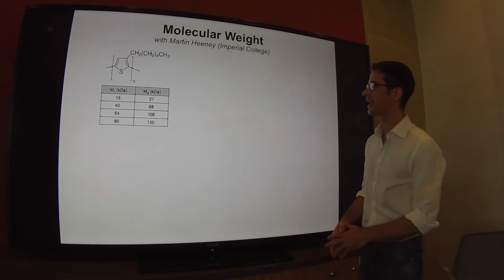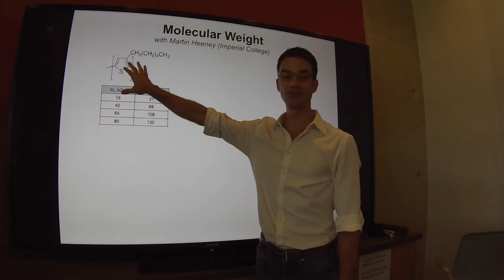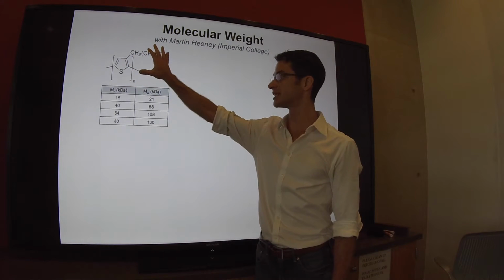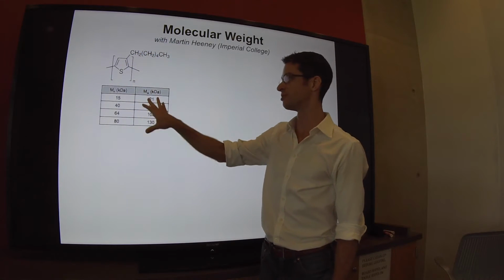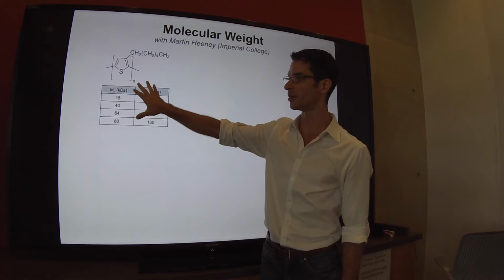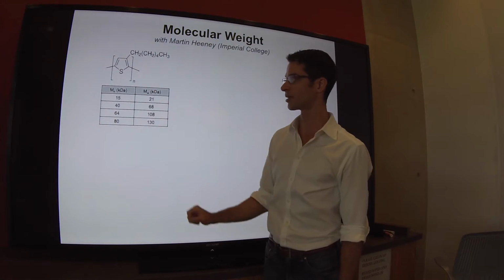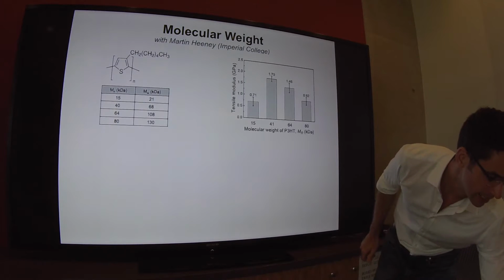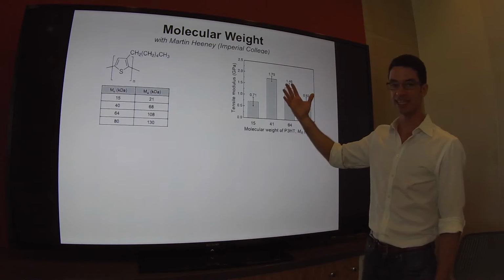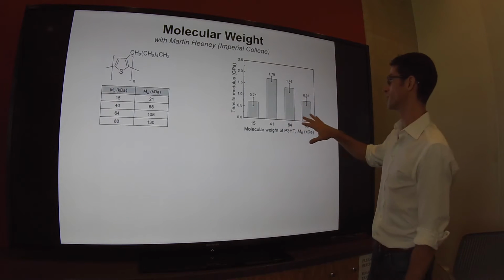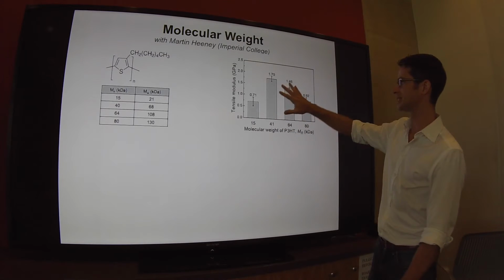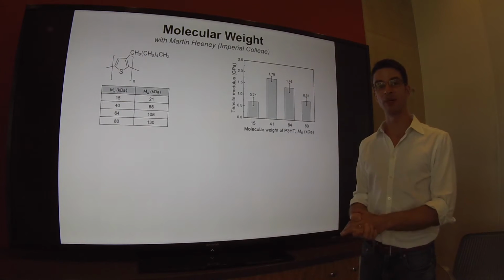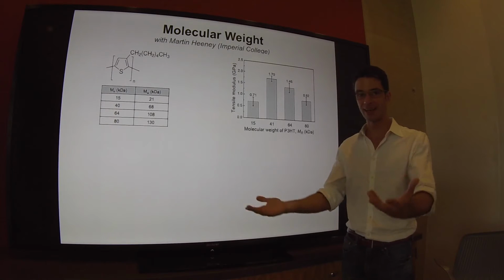Now what does that look like? If we look at just the fruit fly of organic electronics, that is poly-3-hexylthiophene, as a function of molecular weight, so this is done with Professor Martin Heeney at Imperial College, and we plot the tensile modulus, just to take an example, as a function of molecular weight. We can see a trend. We don't expect a monotonic trend here.